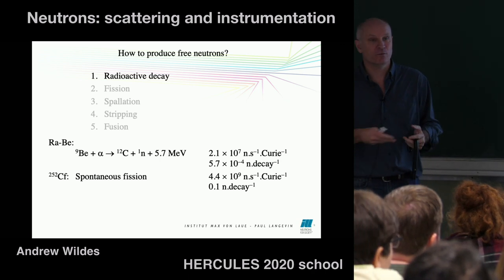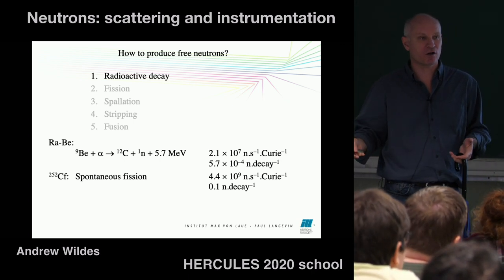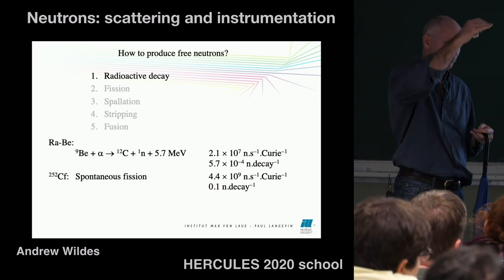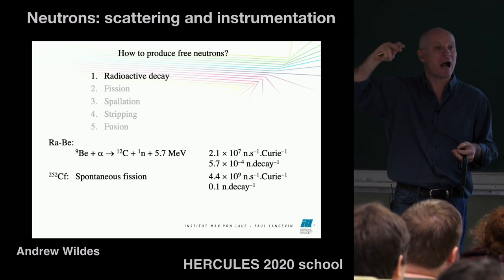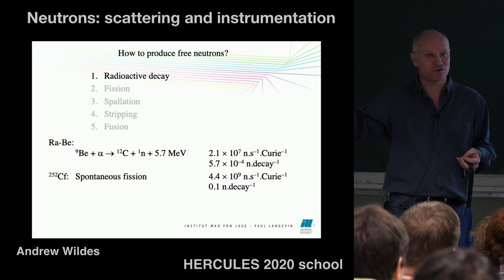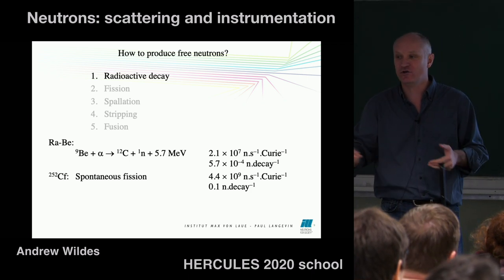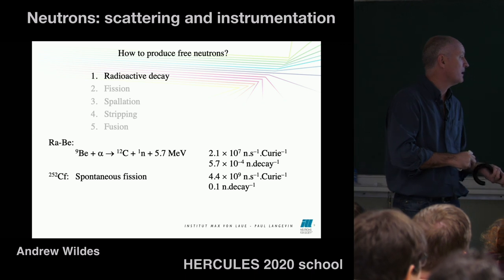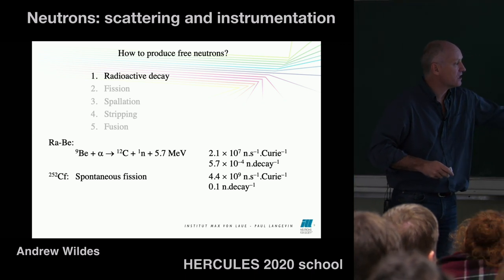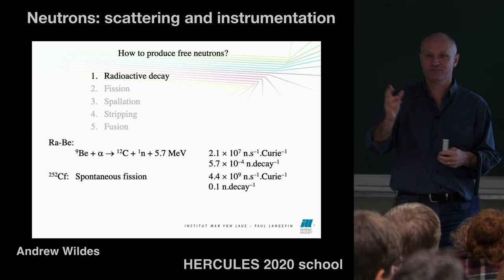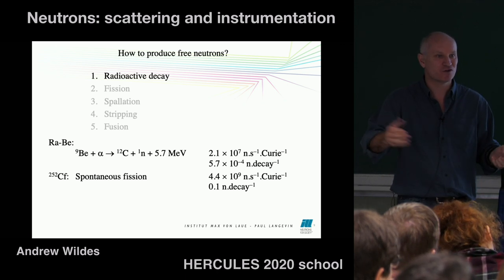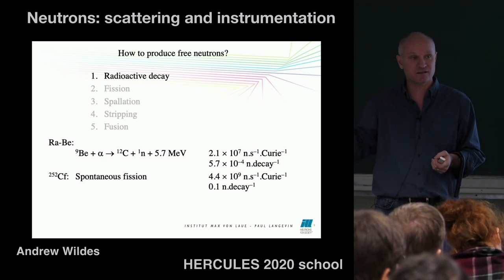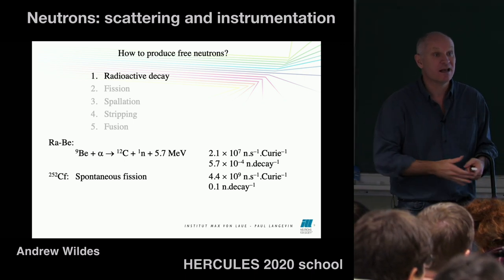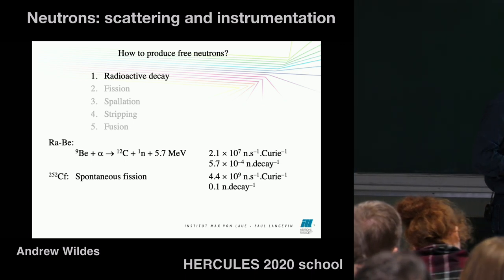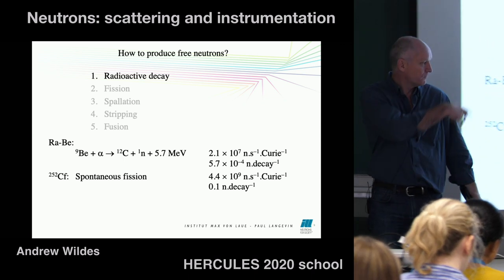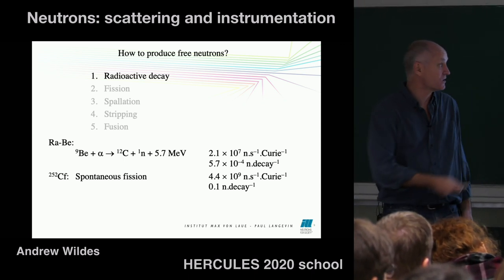These days, we're able to produce isotopes of materials sort of higher than what you might find. Artificially create elements is what we're able to do. These are elements that are not found in nature, and you're able to create that through nuclear technology. This one is called californium, and this seems to be one of the highest producers of neutrons, naturally, if you like. It's not a stable element, it's not a stable isotope. It decays naturally, and it produces about 0.1 neutron per decay instead of 5.7 times 10 to the minus 4, right? So it's much more efficient.